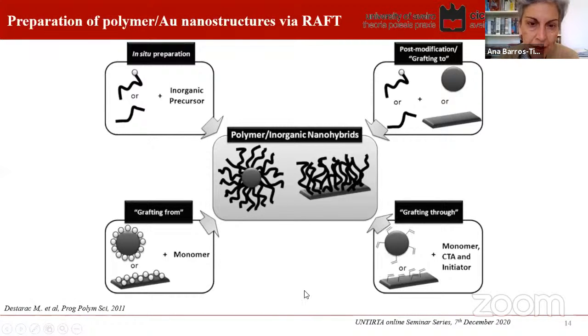So we focused on spherical gold nanoparticles, so nanospheres, but we could have used surfaces or even gold nanotubes, nanorods in particular. I can tell you in advance that we carried out the work with nanorods, not exactly gold ones.